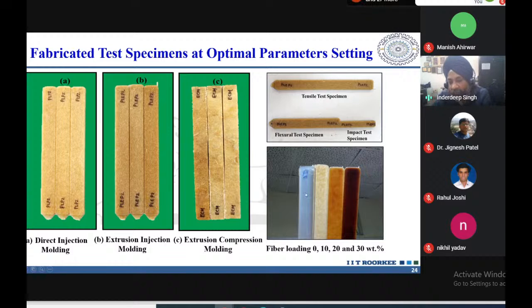And here you see the effect of fiber loading: without any fiber, you get a purely white sample, or a specimen with 10% fiber. This is 10%, then 20%, and with 30%. So we can integrate different weight percentages of fiber and see the effect on the different properties of the developed composite materials.